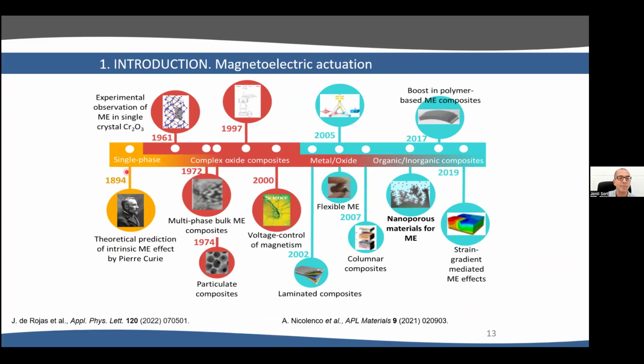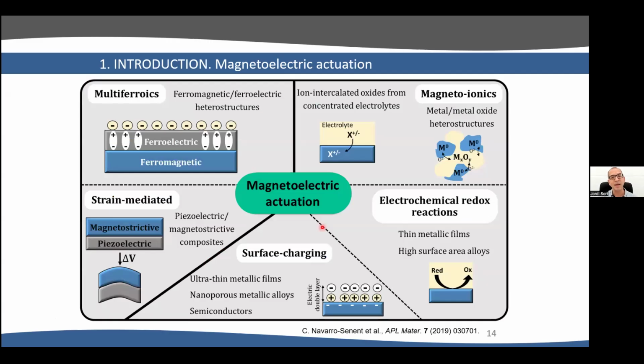And this was the first time that the magnetoelectric effect was observed, using chromium oxide in 1961. After that, there has been a large variety of materials that show this combined action, or combined synergy, between electricity and magnetism in composites, for example, particulate composites, laminated composites, vertically aligned nanostructures, nanoporous alloys, strain gradient mediated materials, and so on. And there are several mechanisms to control magnetism with voltage.